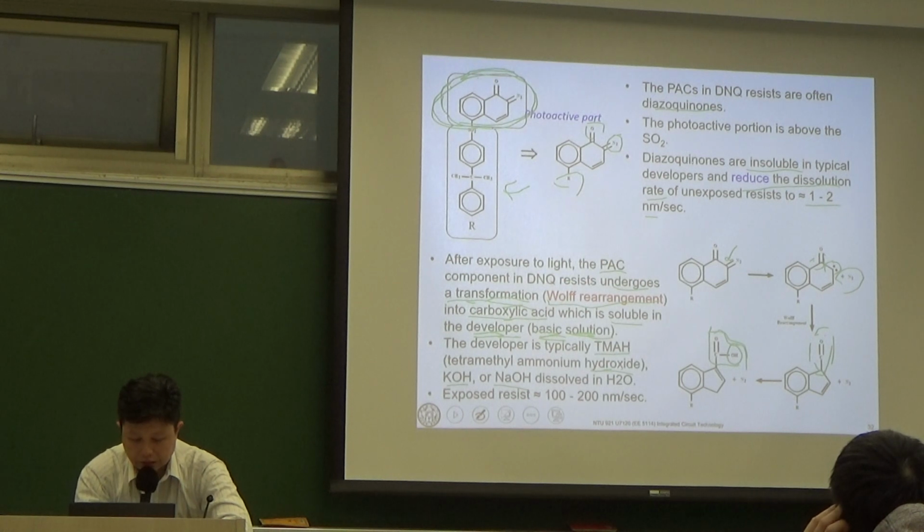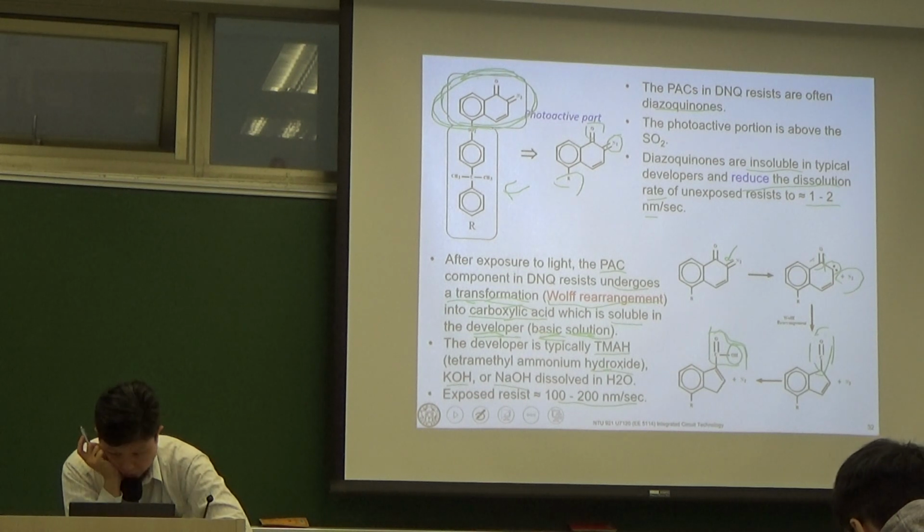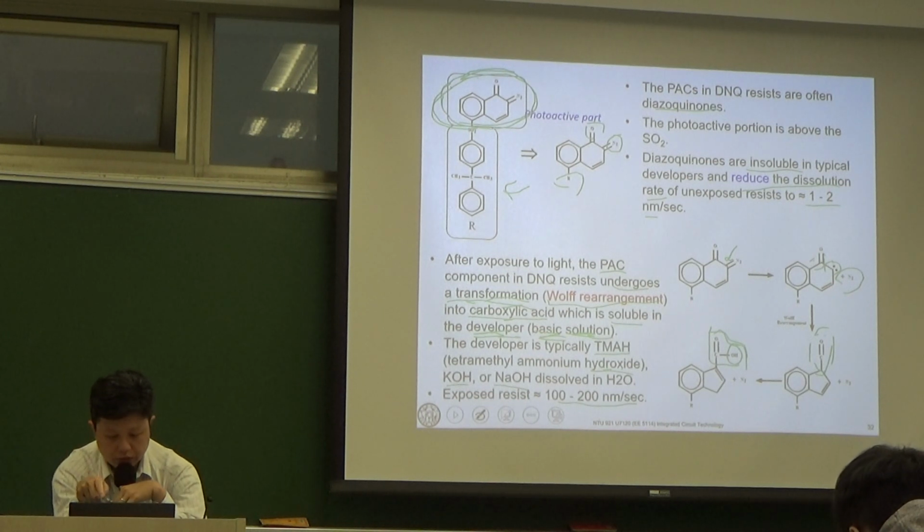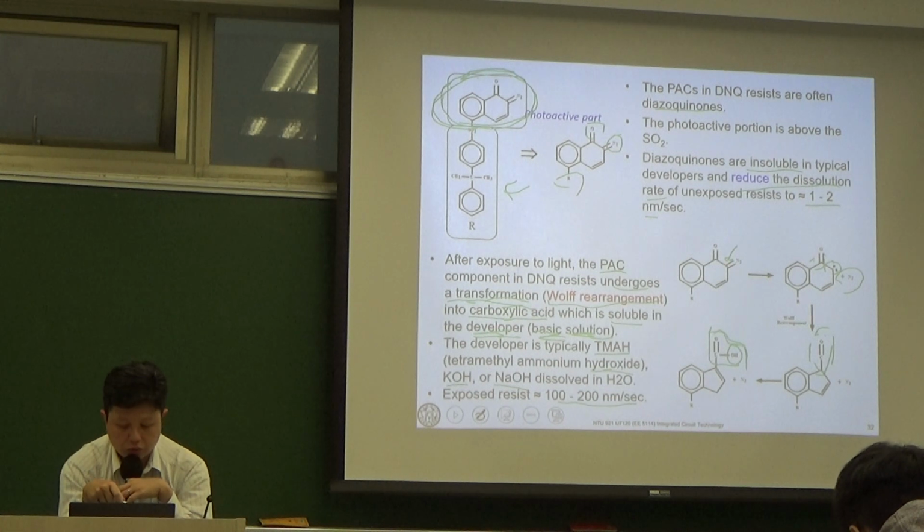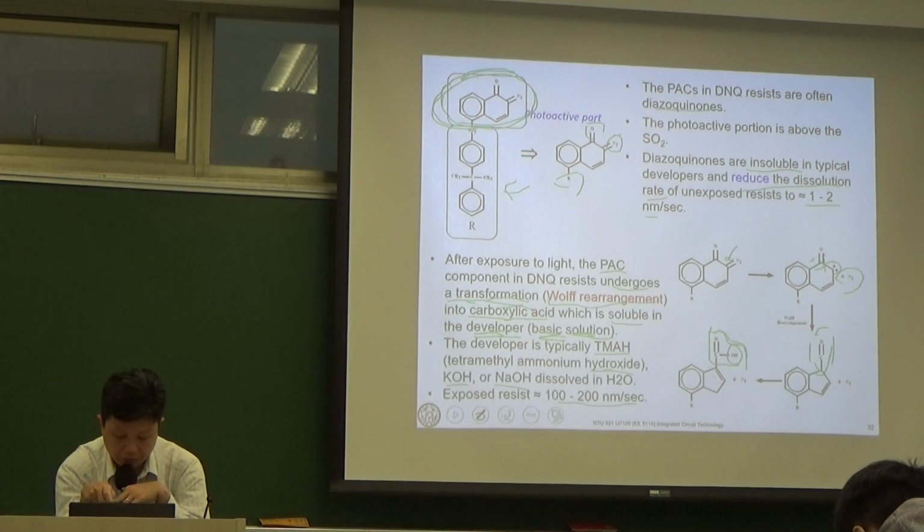Okay, and once the resist is exposed, now the development rate or the dissolution rate will increase by like 2 orders, from like 1 to 2 nanometers per second, and increase to like 100 to 200 nanometers per second.